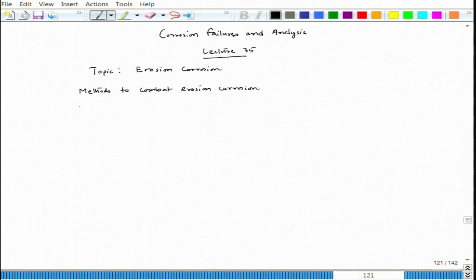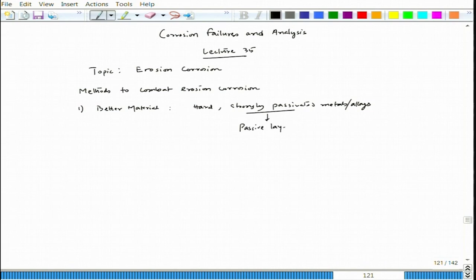Now, when we try to talk about methods, then first thing comes better material. Hard as well as strongly passivated metals and alloys are good. When we talk about strongly passivated, the passive layer should be very hard, not brittle, not excessively brittle, with very good interface bonding.